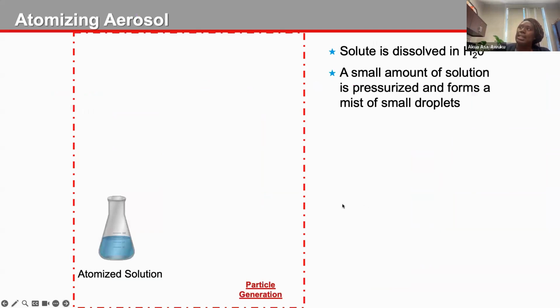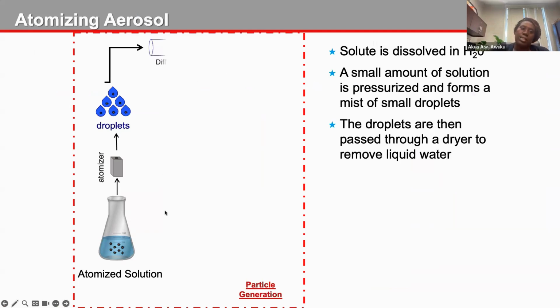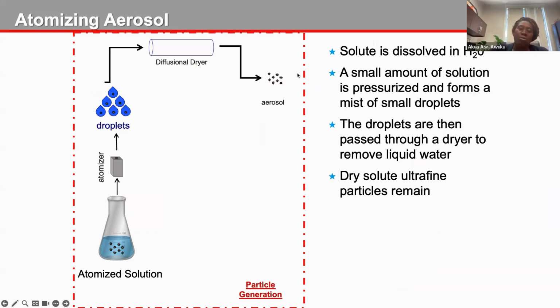So that's what we did. That is, we took that solution, without those pellets, and we essentially passed it through an atomizer. From that atomizer, we create a spray of droplets, and then the spray of droplets is passed through a diffusional dryer. As it passes through the dryer, we get dry aerosol particles. This is a common technique that we use in the aerosol science world, especially when we're trying to generate particles in lab.